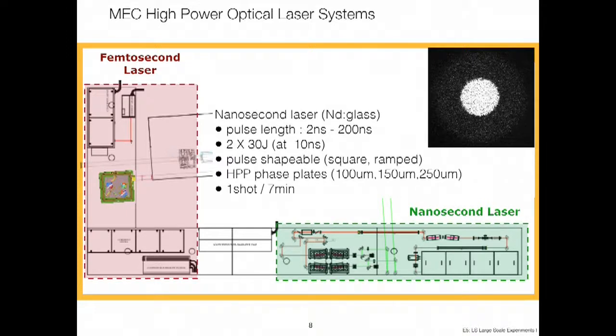And it's generally used with fairly big spots of about 100 to 250 micron and used to drive shock waves into materials. So you drive a shock wave, it goes to very high pressures, and then you probe the state you've created with the X-rays. It's a fairly slow system, so it can only produce one shot every 7 minutes at full power. So you have to keep that in mind.